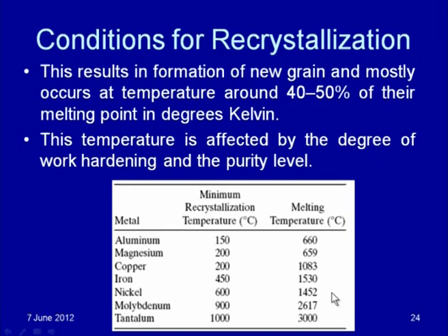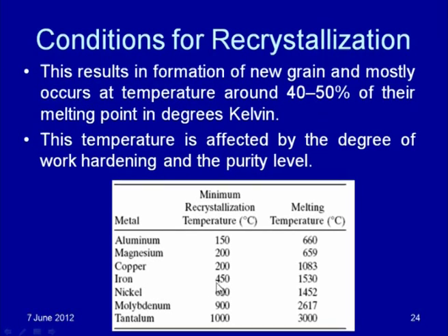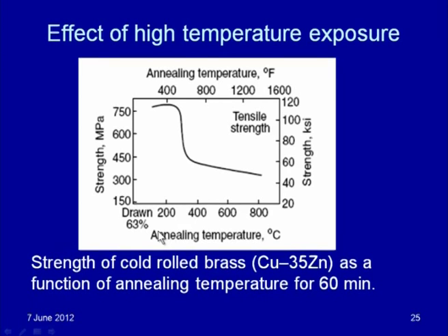This table shows recrystallization temperatures for different metal systems along with their respective melting points. For aluminum, the recrystallization temperature is around 150°C while the melting point is 660°C. For iron, the recrystallization temperature is 450°C and the melting point is 1530°C. Depending upon the metal system, different temperatures are required for recrystallization, and exposure at different temperatures and durations will adversely affect the mechanical performance of the metal.